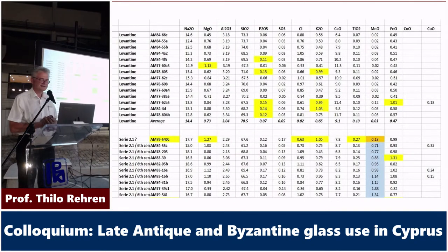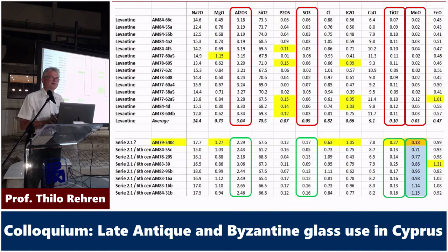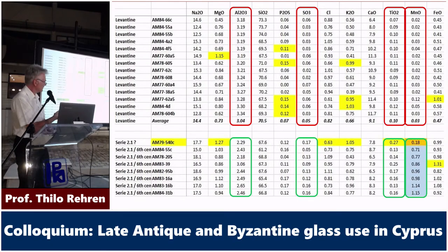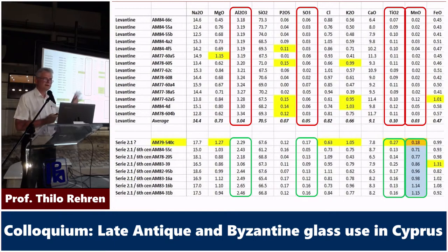Now, I will not spend the next half hour talking you through those numbers in detail, I'm afraid. But I want to highlight very exemplary. We have sorted them here already, Artemios and I. There is glass that we recognize as Levantine, and there's other glass that we recognize as Series 2.1. And if you look at the aluminium values, for instance, the Levantine glass has persistently 3% aluminium. The Series 2.1 has only about 2.5%. The sulfur content is significantly different, much lower in the Levantine, much higher in Series 2.1.